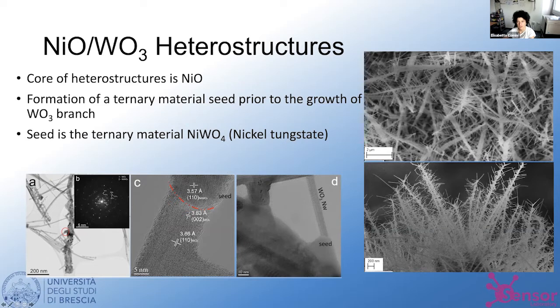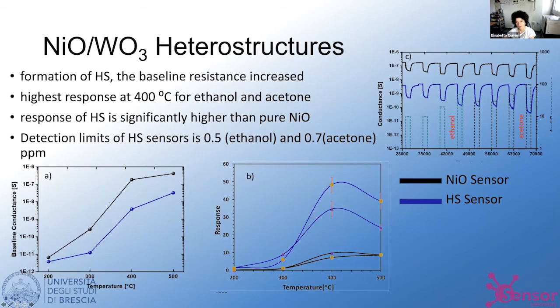In this case, the morphology is really different. You can see here, we have very long growth of tungsten oxide over nickel oxide. And we have also a ternary compound, a nickel tungstate, that is formed in between the junction of these two materials. Even the functional properties are much different. If you look at the conductance over time when we introduce ethanol and acetone, we can see that the behavior of the heterostructure this time is a p-type behavior. So we have a decreasing conductance when we are introducing the volatile organic compounds.